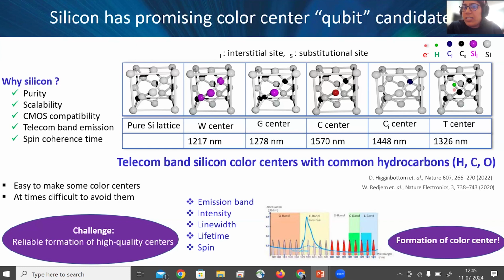You can have a G center when you introduce 2 carbon atoms at substitutional sites inside your silicon lattice, connected to a single silicon interstitial. And if you have this 3 atom pair, you can have a G center, which emits light at 1278 nanometers. And similarly, you can have a CI center and a T center. And that's basically how the structure looks like. And then they give different properties.